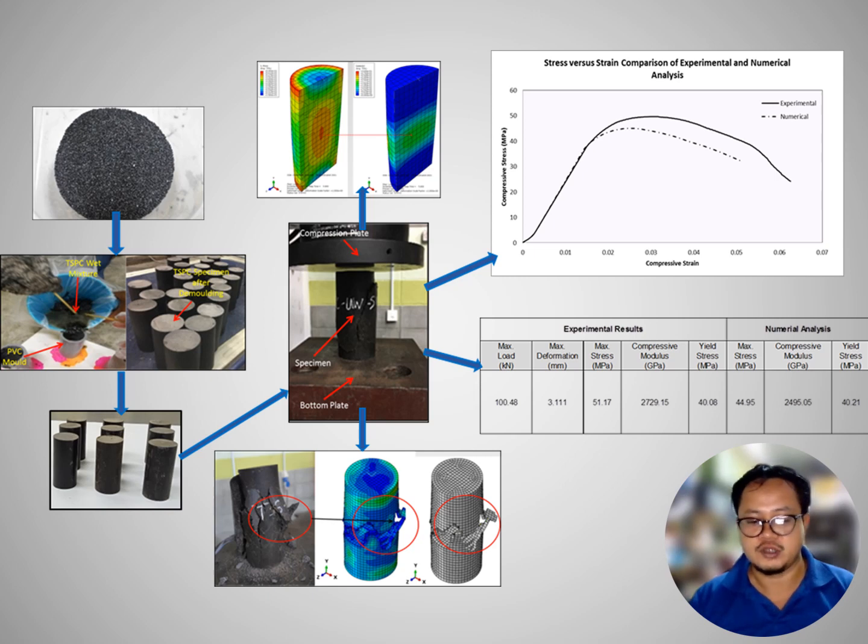The failure mode of test samples has shown crushing failure in the middle of the test sample, but some other test samples have exhibited cracking and shear failure. Therefore, to confirm the general failure mode to be assigned as the tin slag polymer concrete failure specification, there was a need to investigate the tin slag particle distribution throughout the material.